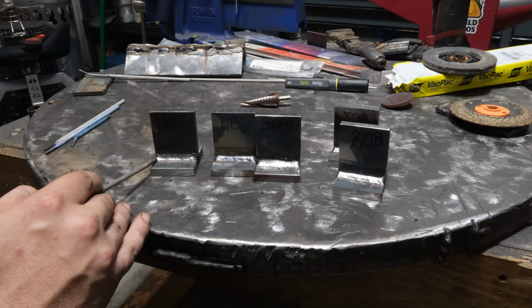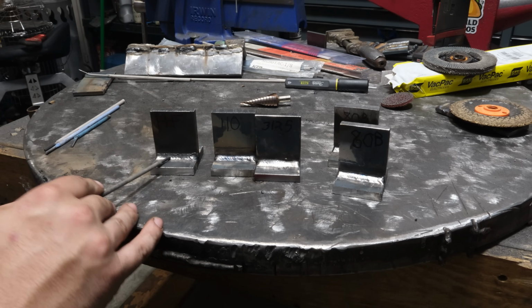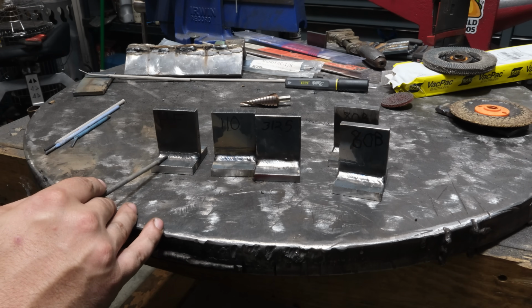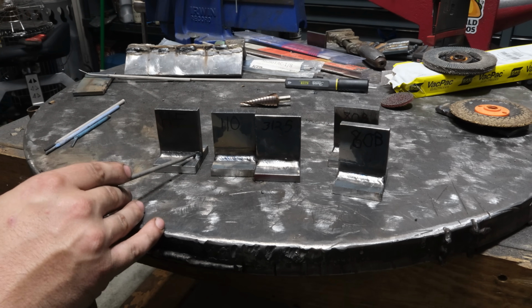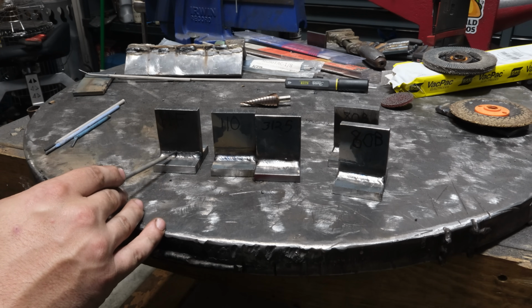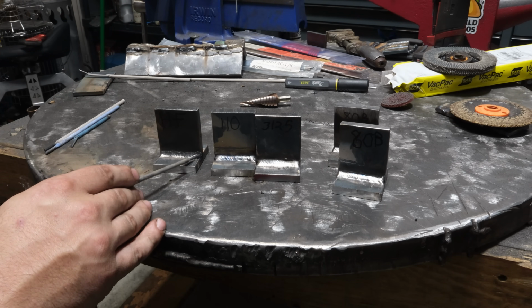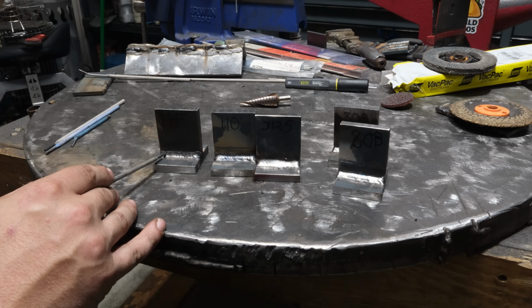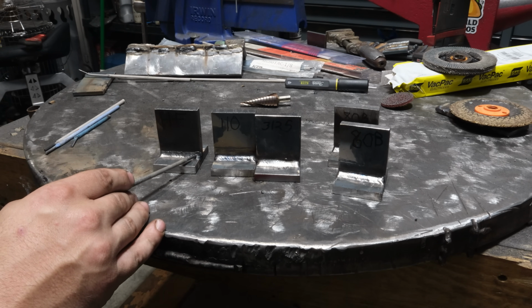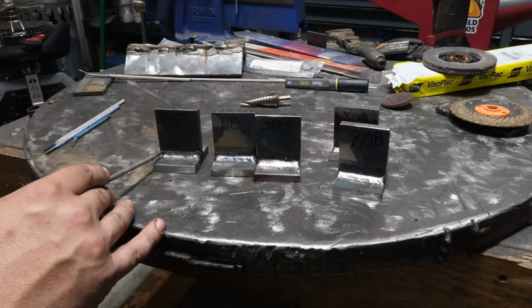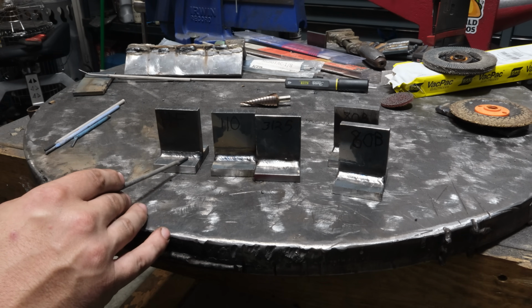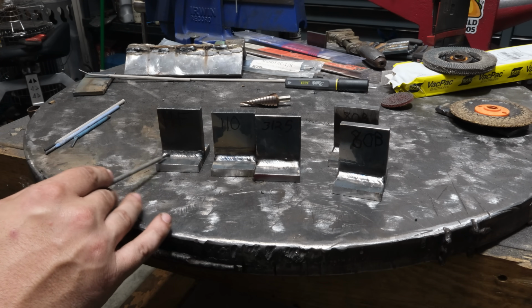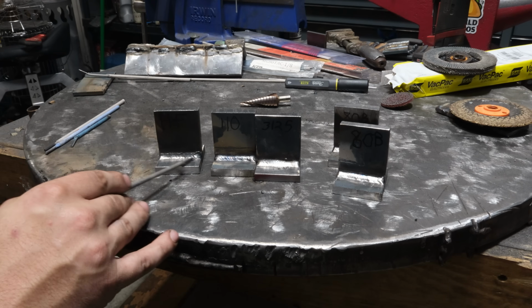I would have to bust out my little microscope to really see up close if that was the case, but I don't anticipate this passing a bend test for a couple reasons. One, I think it's just going to break, and two, it produced a really weird concave bead, so the throat depth of this weld is pretty poor, so that alone I think it's going to end up failing a bend test. But it's a prime example why you probably shouldn't use hard face to weld crap together.